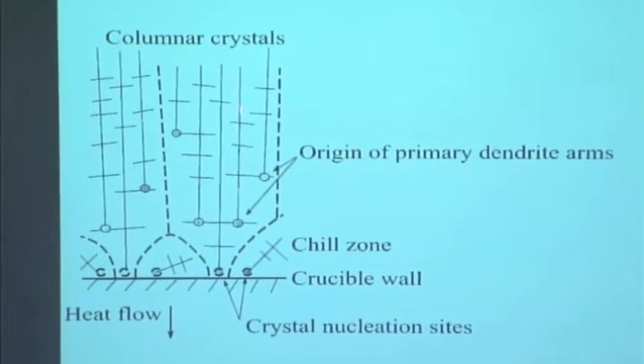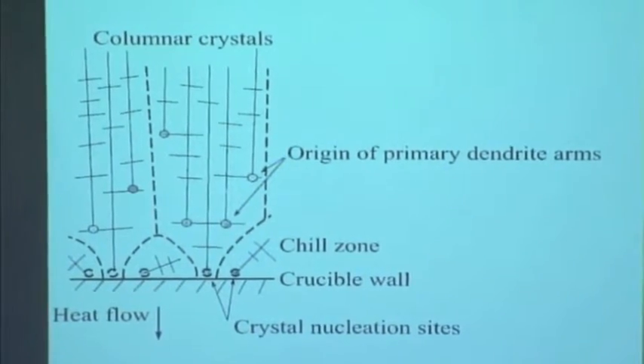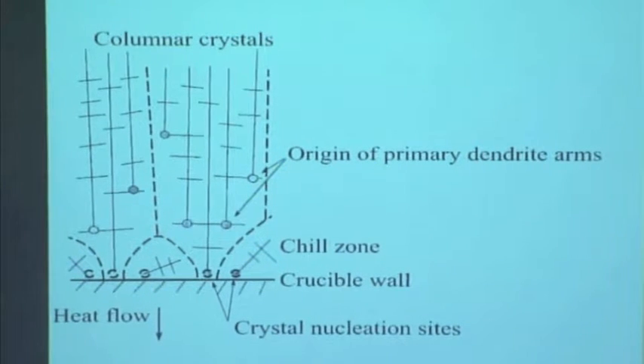Now, next slide, please. Thanks. So this is the structure of these crystals that have this dendritic structure. So you get these crystals with these little dendrites. And the important thing is that these dendrites, that is those elongated structures that you saw, grow in particular crystallographic directions. They also grow in the direction of heat flow. So what that means is that the direction of heat flow becomes a preferred crystallographic direction, and that one gets anisotropy. So we showed this, if you go to the next slide.